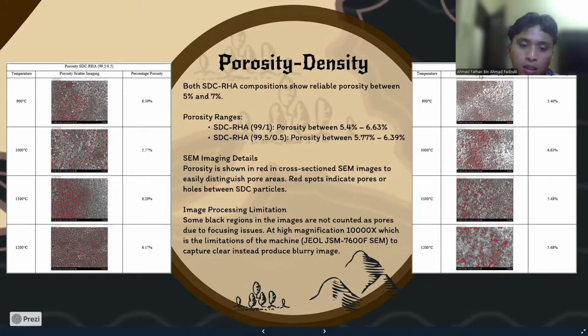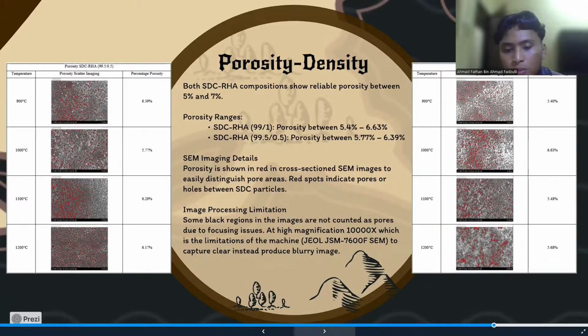As you can see here, there's a red in the cross-section SEM mesh, and this red indicates the pores of the electrolyte. Some black regions in the mesh are not found as pores due to focusing issues. At a high magnification of 10,000 times, which is the limitation of the machine, it captures a blurry image instead of a clear one.